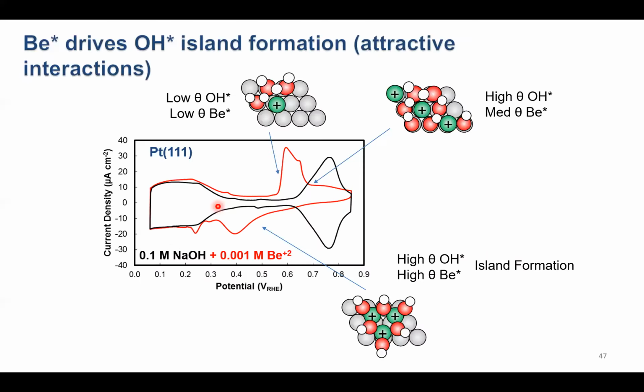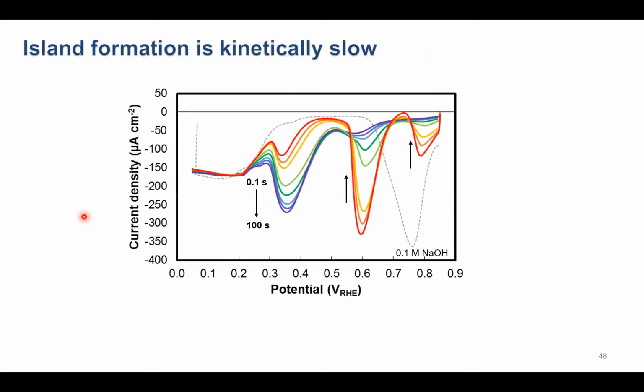And so we can also see this instead of by varying the scan rates, if this is really what's going on, if we really have island formation, we can study the kinetics by just holding the potential at this upper potential limit for varying amounts of time and then scanning negatively very quickly. And so that's what I'm showing here.